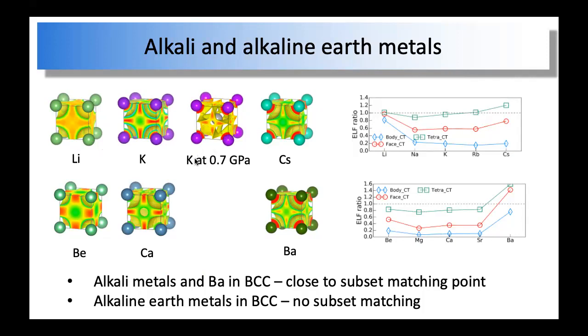For example, potassium, if you compress it to 0.7 GPa, you will shift it to a perfect subset matching point. So therefore, alkali metals are stable in BCC structure under 0 GPa. And if you look at the alkaline earth metals, they are much farther, especially the early alkaline earth metals, much farther from the matching point, and there's some other reason, because their FCC point are actually closer to the matching point. FCC and HCP are closer to the matching point. But again, as I said, the BCC split is perfect.